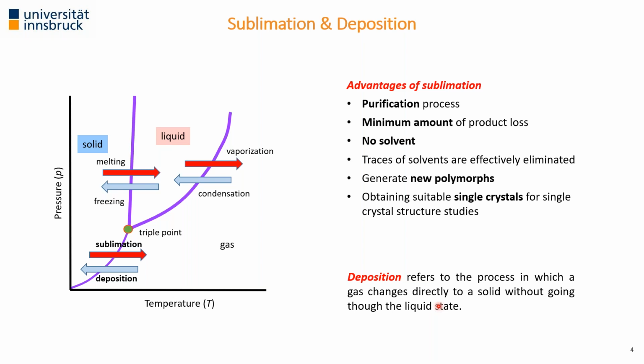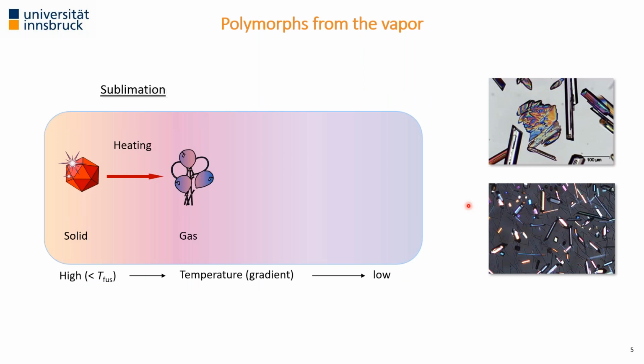Just quickly mentioning, what are the advantages of sublimation? First of all, coming from the chemistry point of view, it's probably the purification process. We have a minimum amount of product loss. And another big advantage for us, especially working in pharma, is that we need only a minimum amount of product. Microscale sometimes even works. We don't need solvents. If solvents are present, for example as residual solvent content, they are effectively eliminated during the sublimation process. And what is especially of interest to me is that we can produce new polymorphic forms through sublimation. Sometimes we are lucky enough to even get really good single crystals which are suitable for solving the structure using standard single crystal experiments.